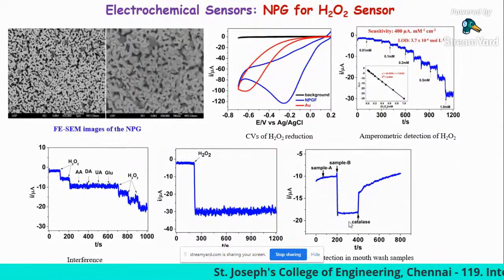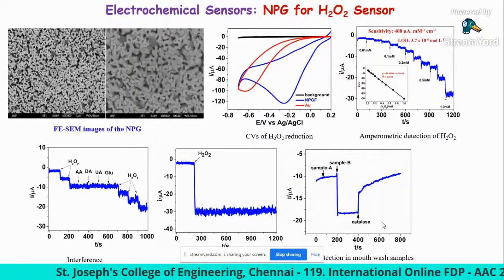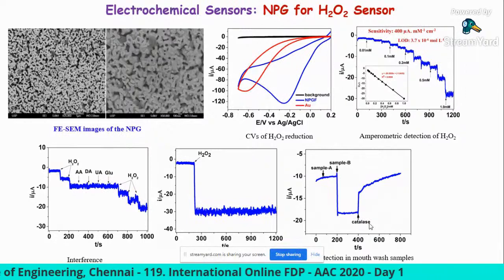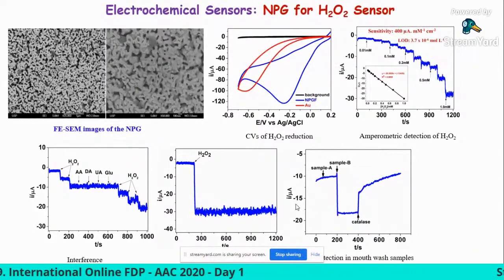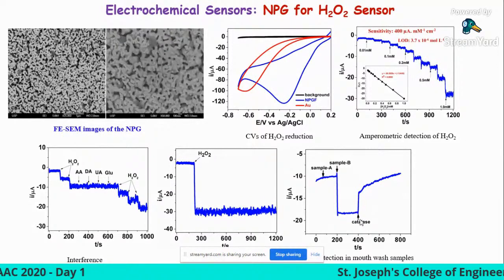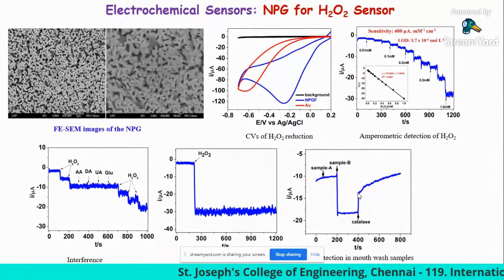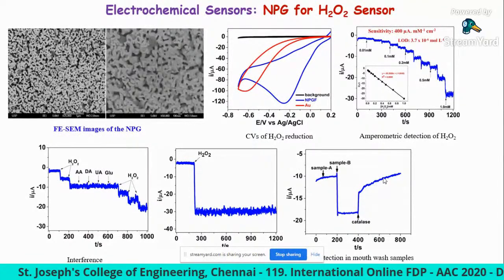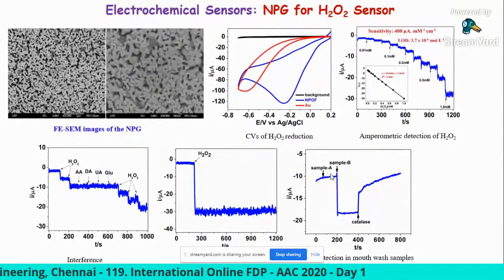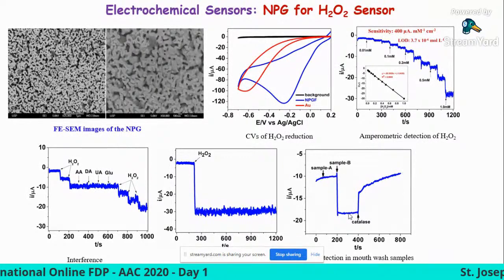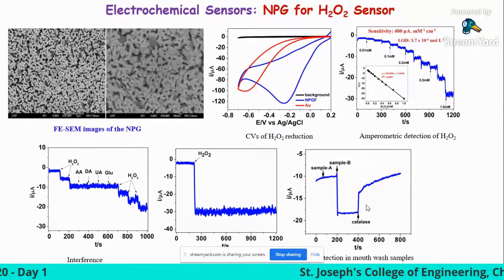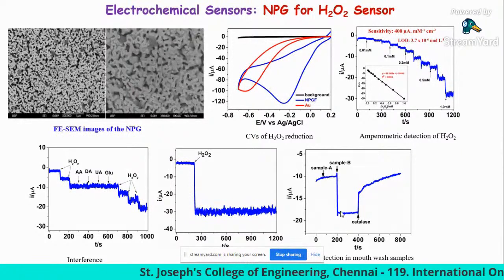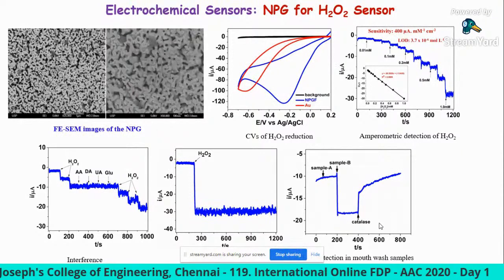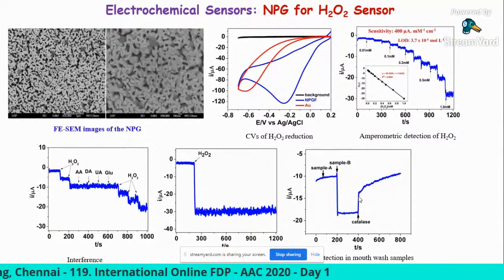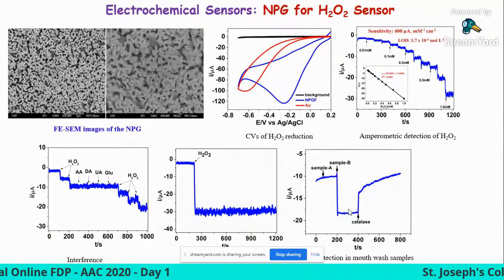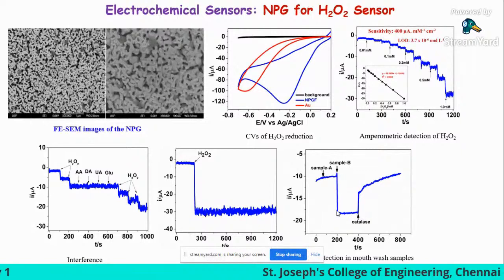In order to prove that, we add the enzyme catalase. This is an enzyme which selectively consumes the hydrogen peroxide from the solution. So we added the catalase into the solution. Then we noticed a decreased current signal initially, and then it takes some time to reach the original background, the oxygen reduction current. So this data clearly confirms the increased current signal is due to hydrogen peroxide, because the catalase is consuming only hydrogen peroxide, not the oxygen. So this experiment clearly shows that the measured current is due to hydrogen peroxide.